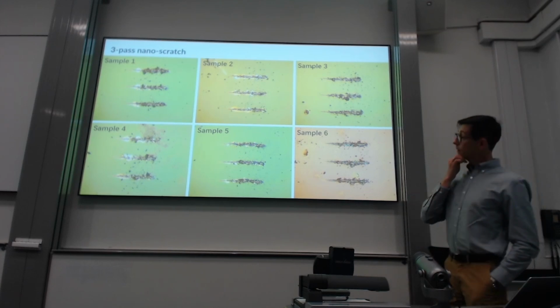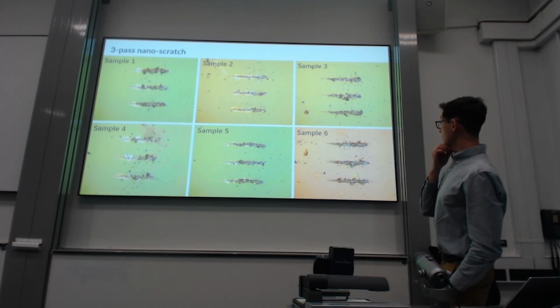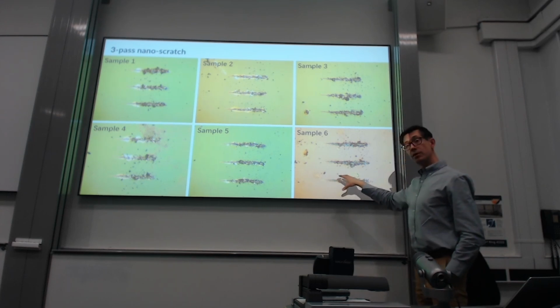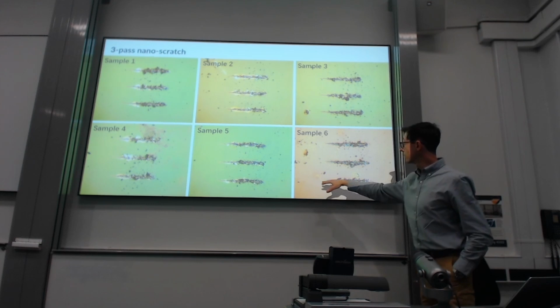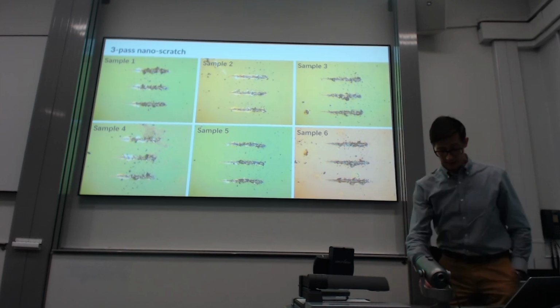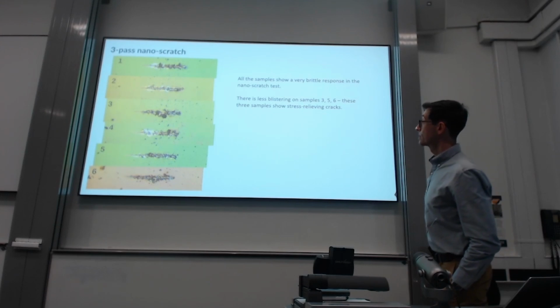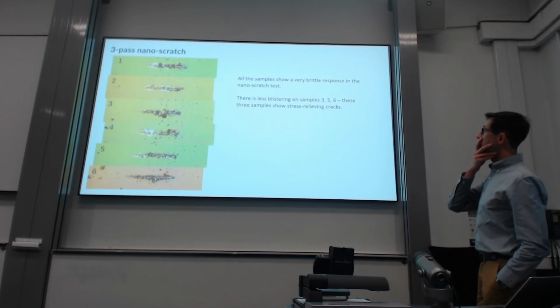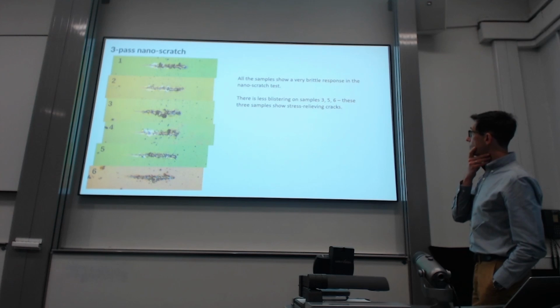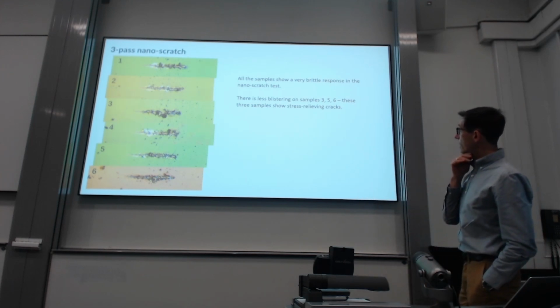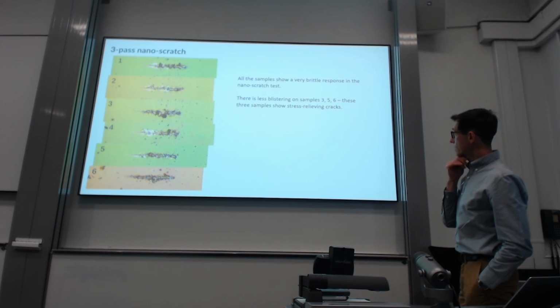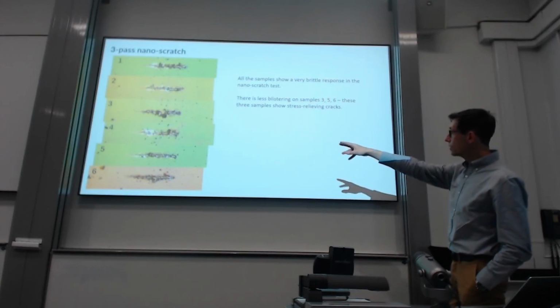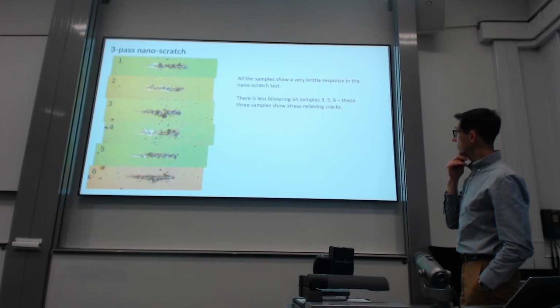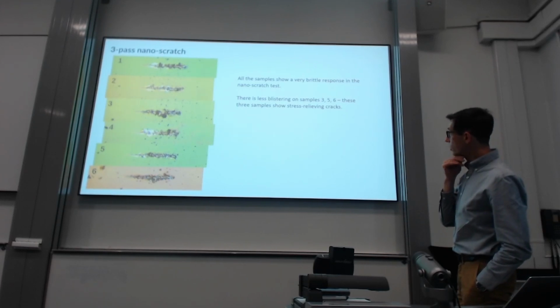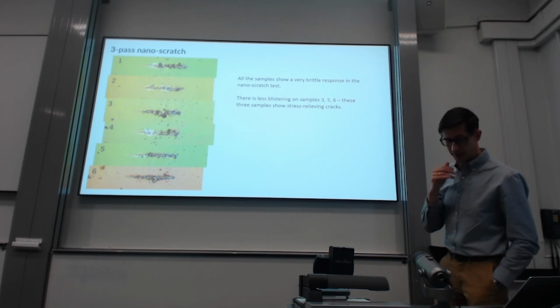So just to show you some optical images of this type of experiment. Each of those scratches represents a combination of 3 passes: low load, ramp load, and low load again. And just to compare 6 samples, 6 variants of the coatings, this is the representation of those samples. So I think all samples show a very brittle response, clearly looking at the images in this type of experiment. Perhaps there's less blistering on samples 3, 5, and 6, and these show stress relieving cracks if you look at them.